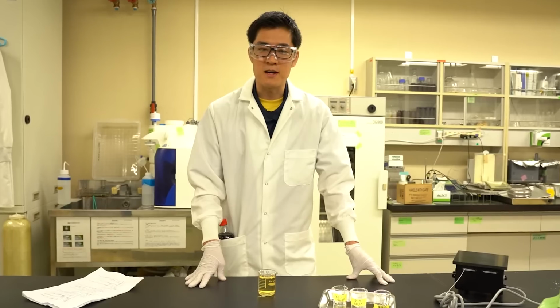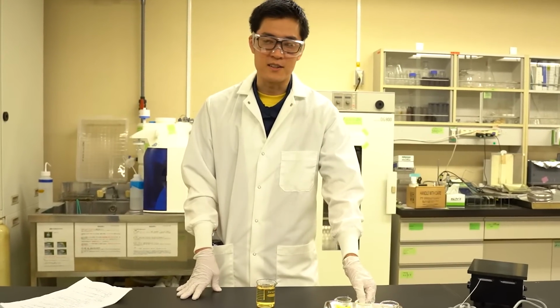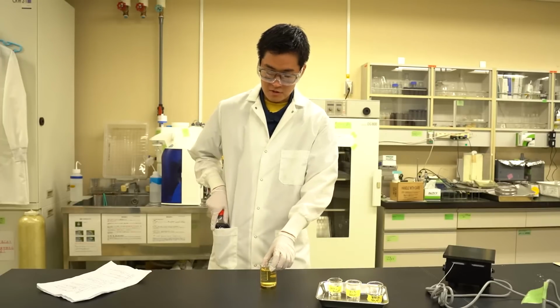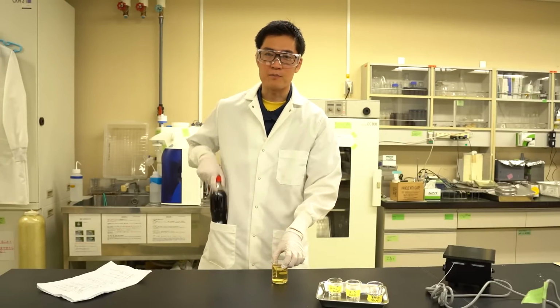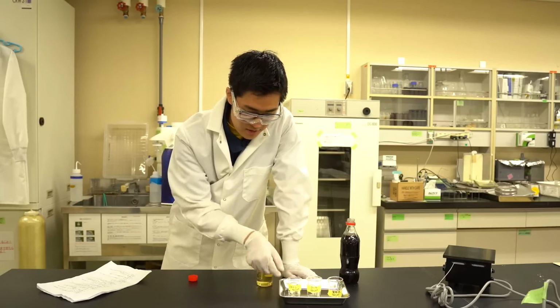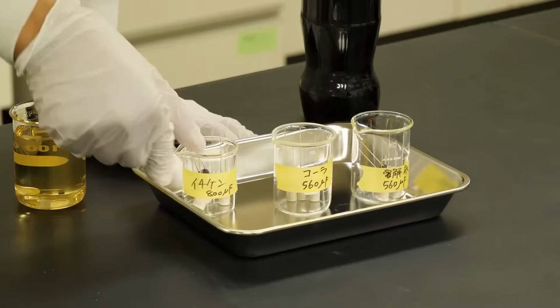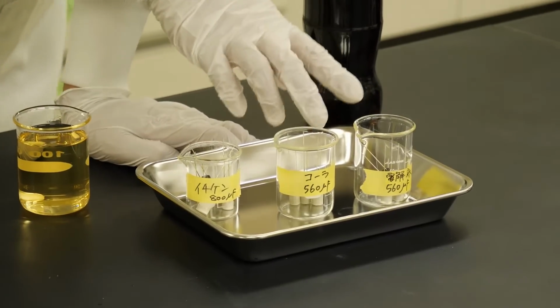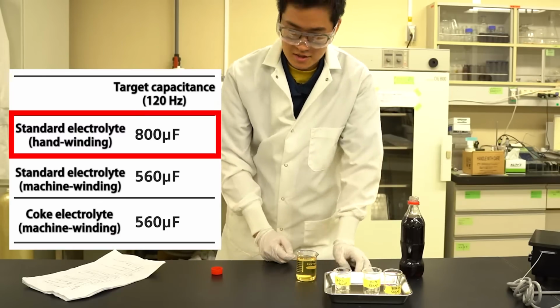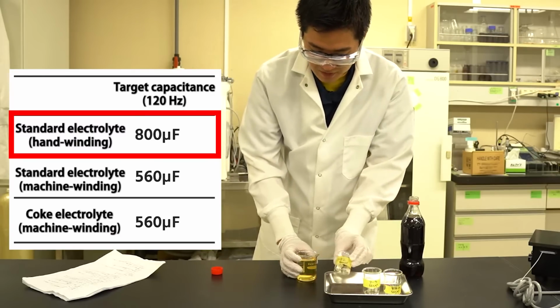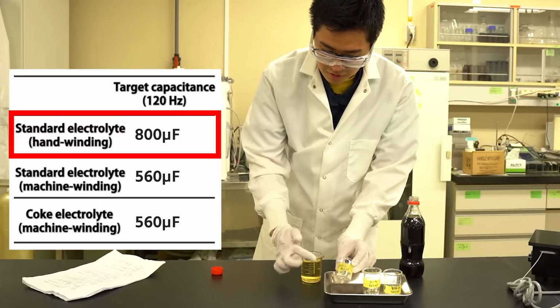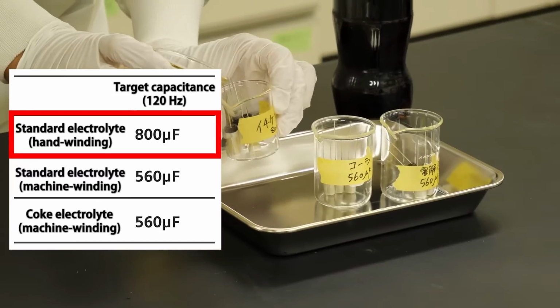Actually, any liquid can serve as electrolyte as long as it contains electrolyte. So today, in addition to the electrolyte I mixed, I prepared another liquid, this black liquid. I'll use this black liquid as another electrolyte. There are 3 beakers. One is for the elements I wound manually. The other 2 are for standard electrolyte and that black liquid. I'll perform impregnation on these 3. Firstly, the elements I wound. The target capacitance is about 800 microfarad.